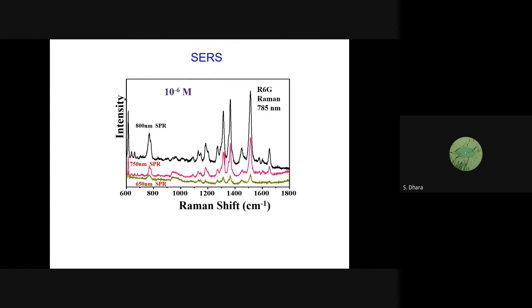And there you confine the light, and once you confine the light, the Raman phenomenon increases by a maximum of the order of, I'll give you an example, I'm going a bit slow, 10 to the power 8 times. So here we could show that we could even detect up to 10 to the power minus 6 molar of a particular reagent called rhodamine 6G, which is normally taken. Methylene blue is also taken. They are less responsive, because we cannot play every day with biological samples, which requires a license. R6G is also a very dangerous carcinogenic element, but we take precautions to handle it.